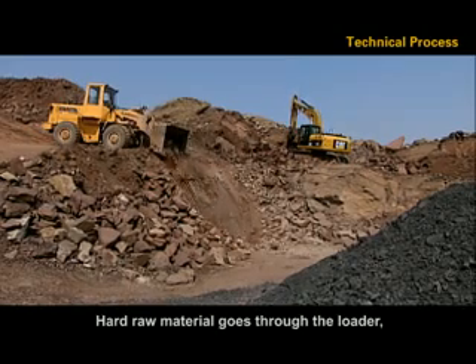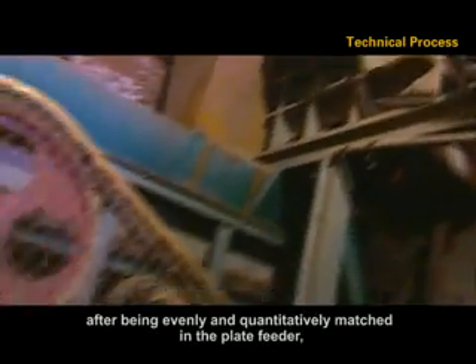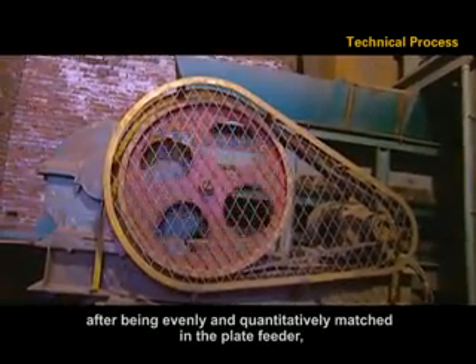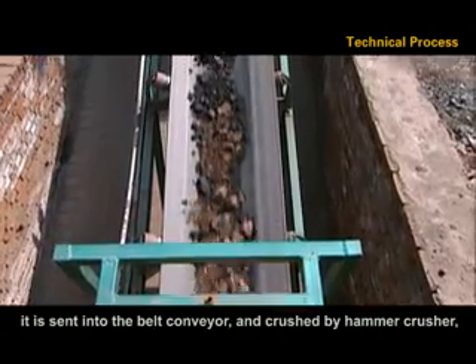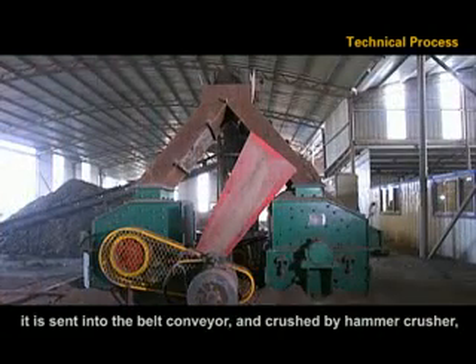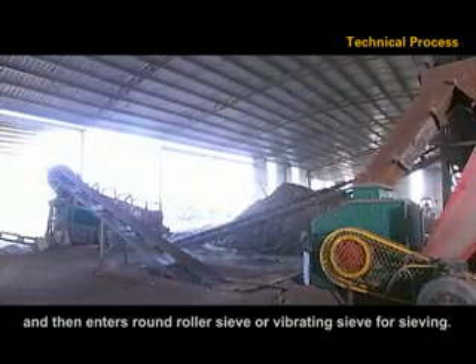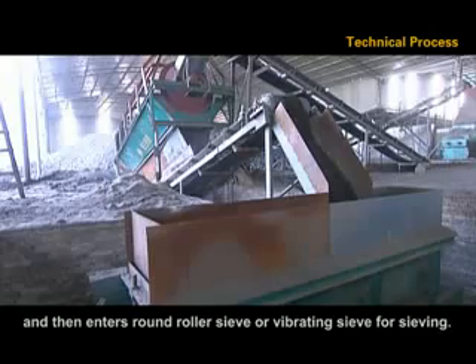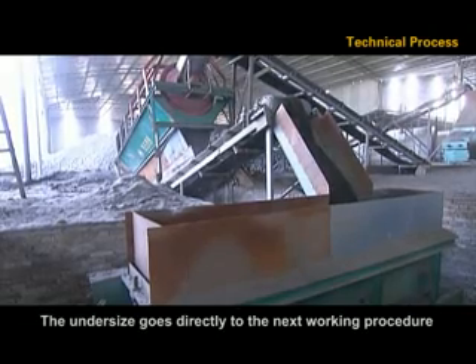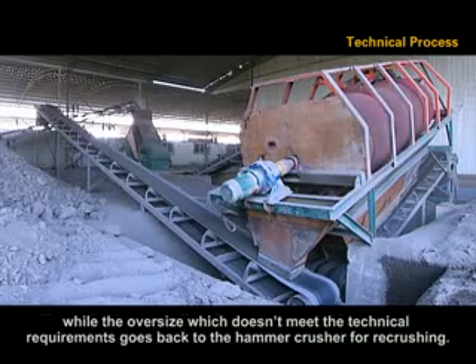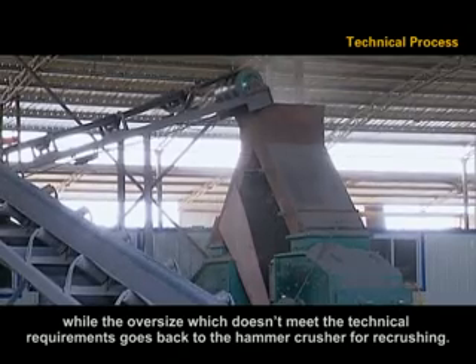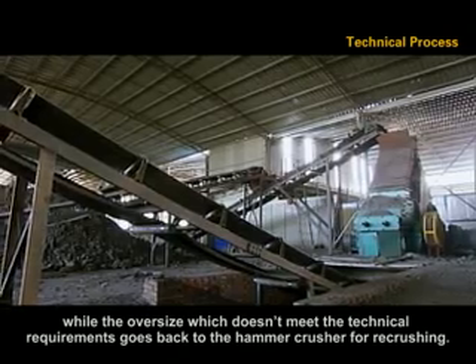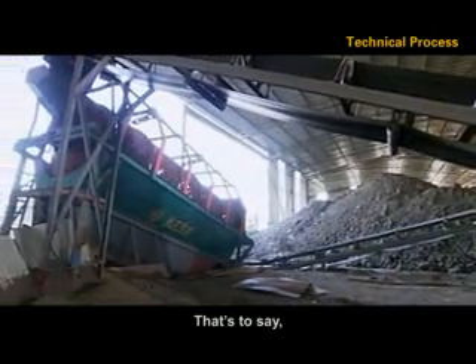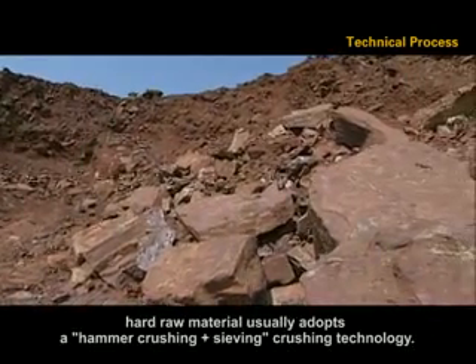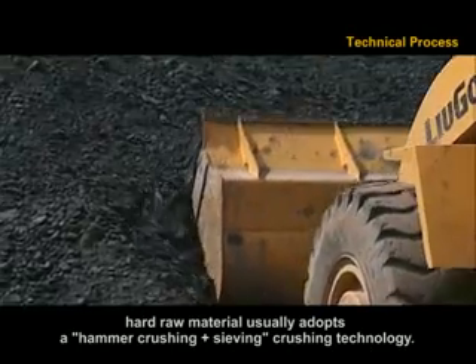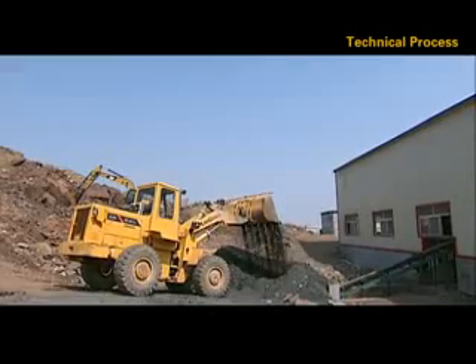Hard raw material goes through the loader after being evenly and quantitatively matched in the plate feeder. It is sent into the belt conveyor and crushed by hammer crusher, and then enters round roller sieve or vibrating sieve for sieving. The undersize goes directly to the next working procedure, while the oversize, which doesn't meet the technical requirements, goes back to the hammer crusher for re-crushing. That's to say, hard raw material usually adopts a hammer crushing plus sieving crushing technology.